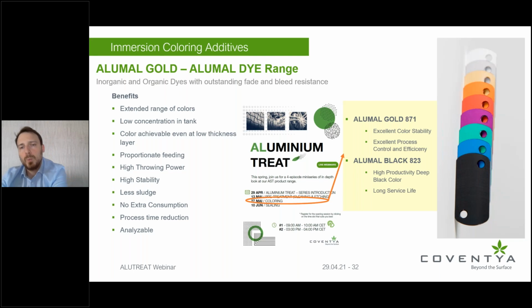The first group that we will be mentioning are the Aluminium Gold series, which is basically iron-based chemistry that provides you the gold colors. And this chemistry, again, even the raw material is synthesized by us, has excellent color stability in terms of UV and color distribution, but also excellent process control and efficiency, especially compared to some powder products that are currently out there.